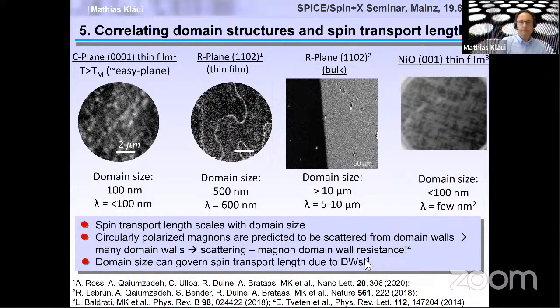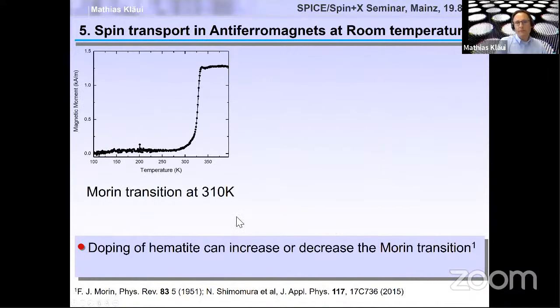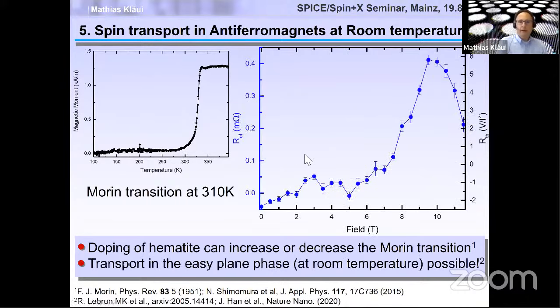And then let me show you some recent results as the final two slides, that actually by doping, we can change the Morin transition. For instance, here, we can switch the Morin transition from below room temperature to above room temperature to get transport in the easy axis phase at room temperature, or we can even transport spin in the easy plane phase at room temperature, which was also shown here by our colleagues in this Nature Nanotechnology paper, which came out, and our paper here as well. So even in the easy plane, there's a possibility, due to the superposition of linearly polarized spin waves, to have a net spin transport.